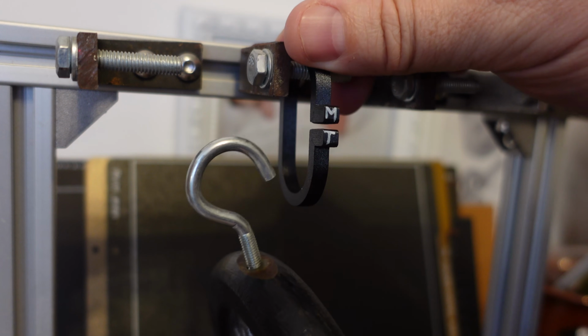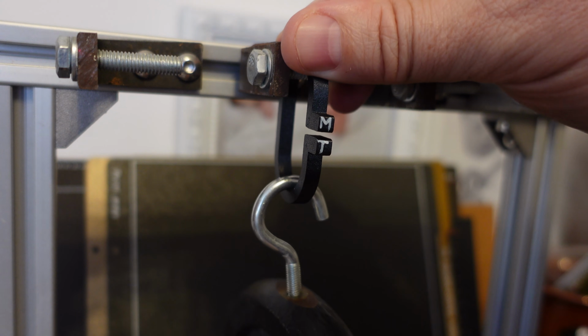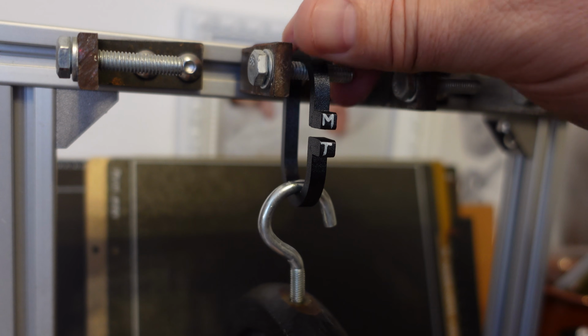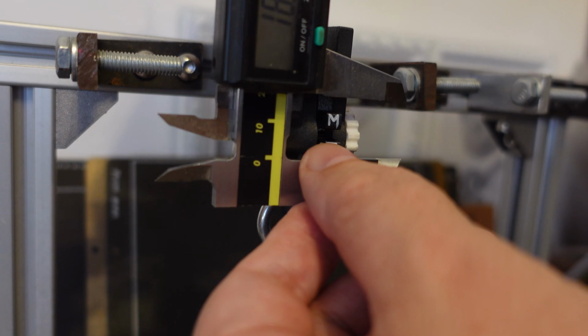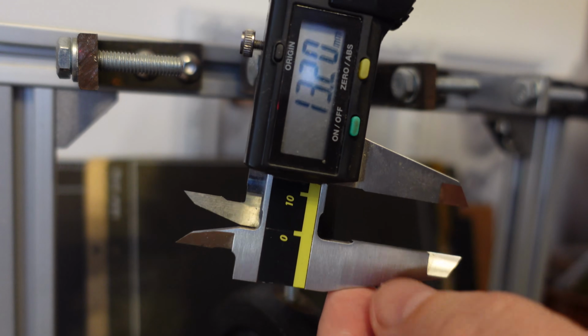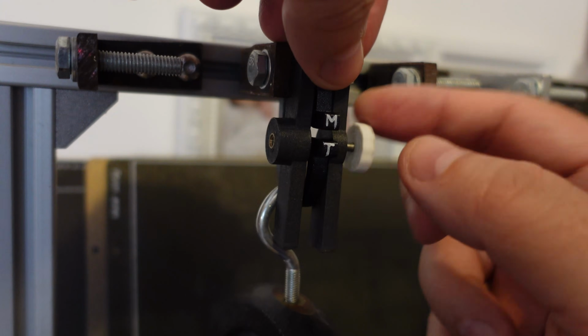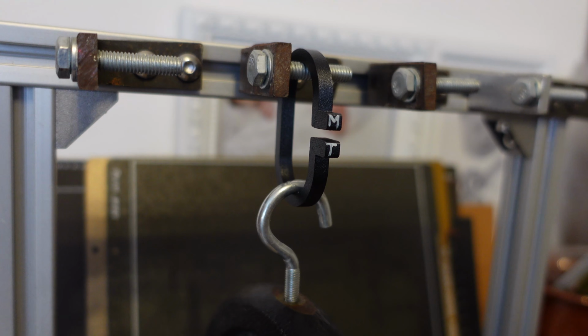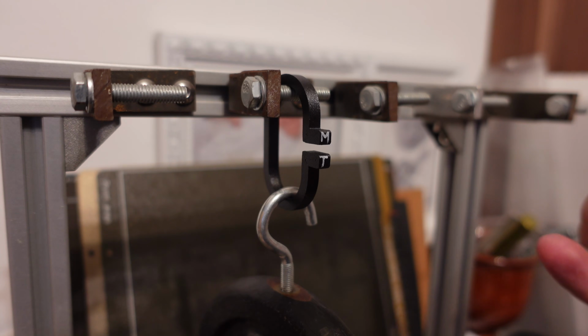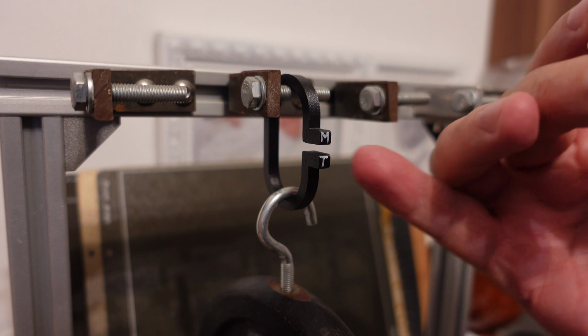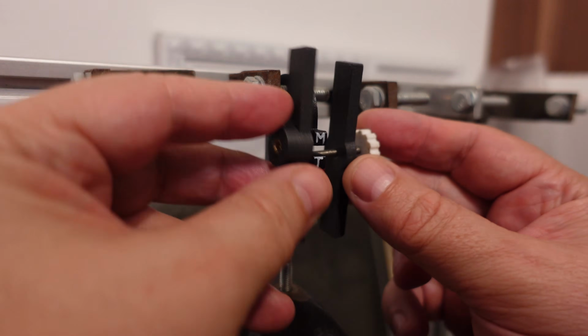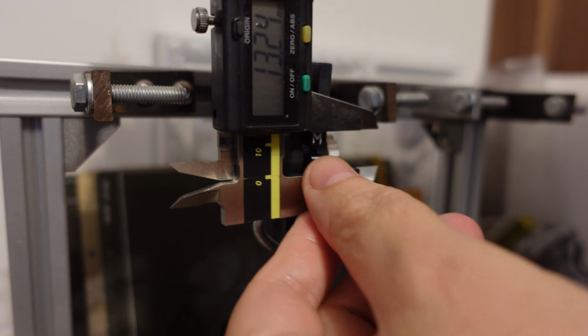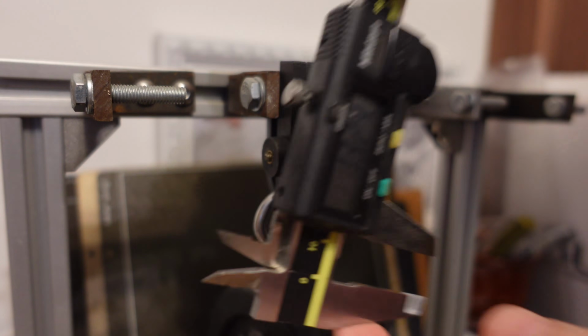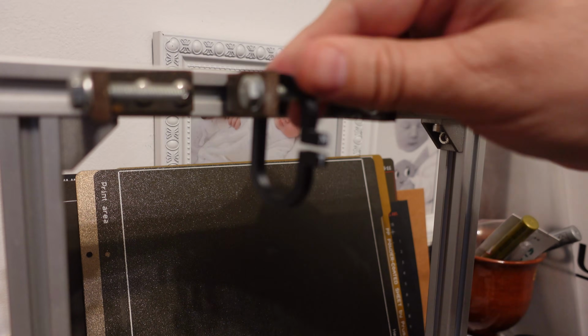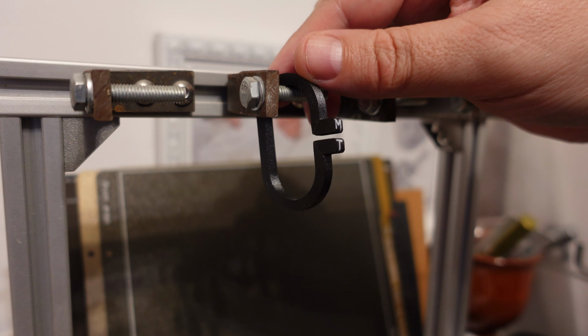Creep test, the deformation under constant load of 1.25 kilograms, which probably will be very small. Not so small as I thought. 13.20. And now let's jump in the time. Last day of measuring, visually no changes, but let's measure it. 13.24. Same like at the beginning.